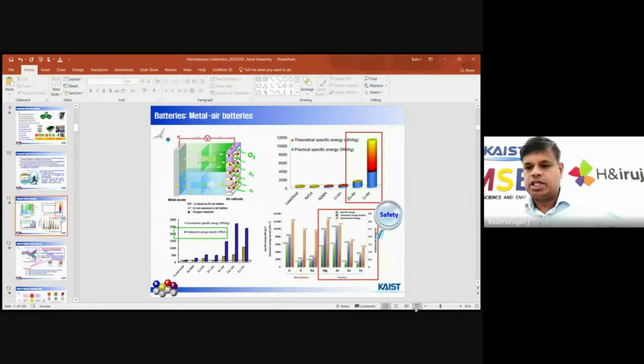And the metal air battery, you can see. So what is the mechanism of a metal air battery? Usually in the air cathodes, they are doing ORR and OER mechanisms. And whatever metal we are using, we call it lithium or zinc. Usually when we use lithium, we call it a lithium air battery. When we use zinc, we call it a zinc air battery. There are many types of metal air batteries available, but why do we choose the zinc air battery rather than the lithium air battery? Because when we use the lithium air battery, we have to use non-aqueous electrolytes. We cannot use aqueous electrolytes. But when we go for the zinc air battery, we can use aqueous-based electrolytes.